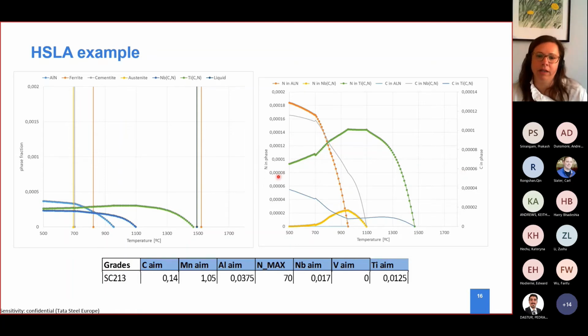In this case, what is plotted here is nitrogen and carbon. Again, the same precipitates: niobium, aluminium, and titanium carbonitrides. Aluminium, we know that it's going to be aluminium nitride. So here we have it. It's only aluminium nitride, and it has only aluminium and nitrogen.